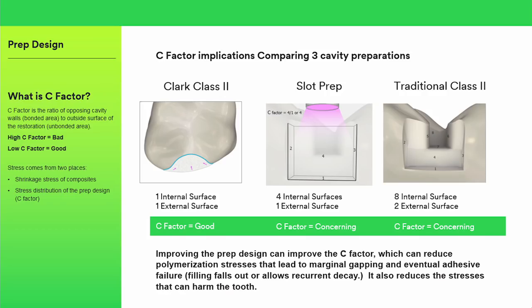So this is a great slide that really talks about C-factor, and I've got some other lectures talking about C-factor, so I don't want to spend a lot of time. But C-factor, which is really an explanation of the problems with polymerization shrinkage, as the composite shrinks away from the cavity walls, it's always a problem. And so we've tried to mitigate the polymerization shrinkage by layering or reduce stress. Shrinkage is still a problem. But when we change the cavity preparation so that it becomes, number one, a compression joint, and number two, a very flattened preparation, the C-factor becomes favorable.